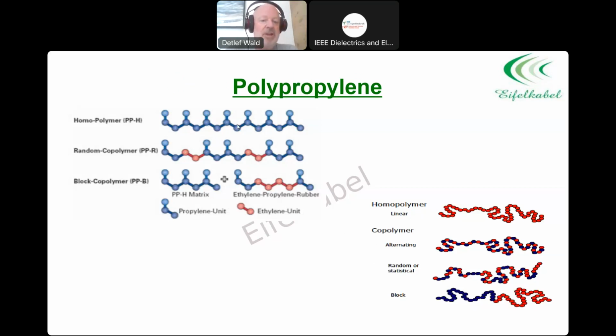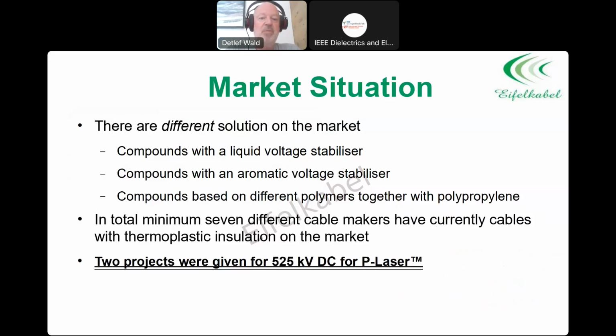Mainly for cable application, we're speaking about something different. We're speaking about copolymers. That means you copolymerize polypropylene with a second monomer, ethylene, hexene, or butene, and you get a random copolymer or a block copolymer. Random means that randomly you have the comonomer distributed in the polymer chain. A block copolymer has a block inside the polymer chain that gives you specific different properties than a random polymer. I will not speak too much about chemistry, as I know that most of you are electrical engineers, so I don't want to bore you. If you have other questions, please ask them at the end.